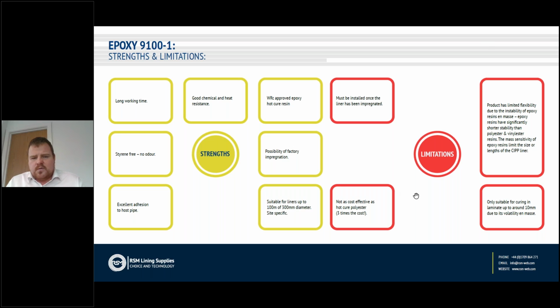In terms of the limitations of the use of 9100-1, the liner does only have a finite amount of working time. With polyester, it is possible to store liners possibly up to 7 days. With epoxy, ideally, within 24 hours, the material needs to be installed after impregnation. Epoxy obviously is a little bit more costly, but you do get the added benefits of adhesion, no styrene, and the excellent chemical and heat resistance that epoxy brings.